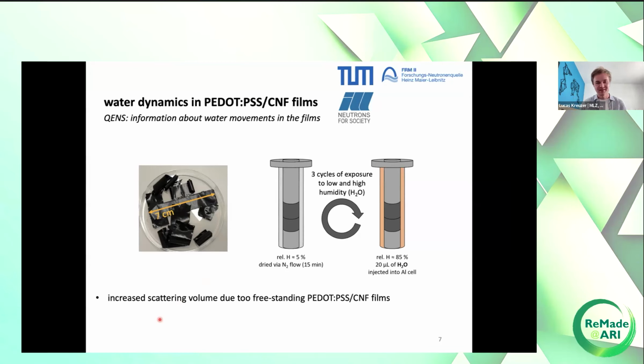So for a thin film physicist, 10 microns, which is the thickness of these films, is not thin. But this is somehow a compromise of having a reasonable scattering volume, meaning reasonable measurement times, but still also reasonably thin films, even though they are in a micrometer range. For the measurement protocol, here we have now 3 cycles of exposing them to low and to high humidity. So we dried them simply by a nitrogen flow, then closed the cell and measured it. It was the dry measurement. And for the humid ones, we injected 20 microliters of water into these cells, let them equilibrate for a couple of hours, and measured them then at this IN5 instrument.